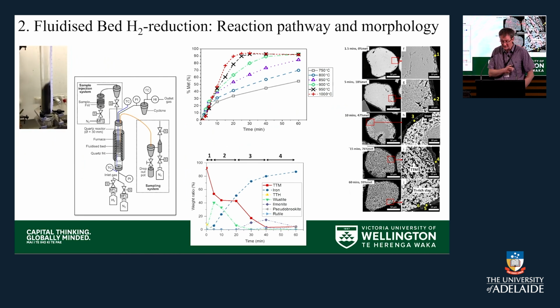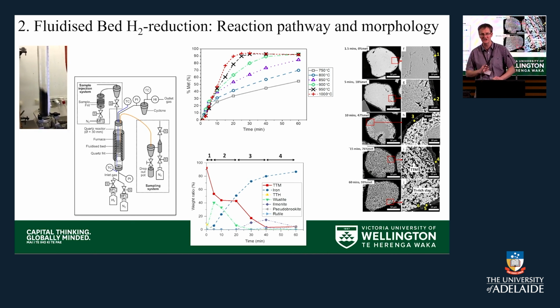But just moving quickly, we've also done quite a bit of work on fluidized bed reduction. This is showing our material fluidizing. It's a beautiful material to fluidize. It's got nice high density, 5 grams per cubic centimeter, nice and round. And that allows us to put reasonable amounts of hydrogen through it, and we can do some process mineralogy, because both minerals and metallurgy matters.